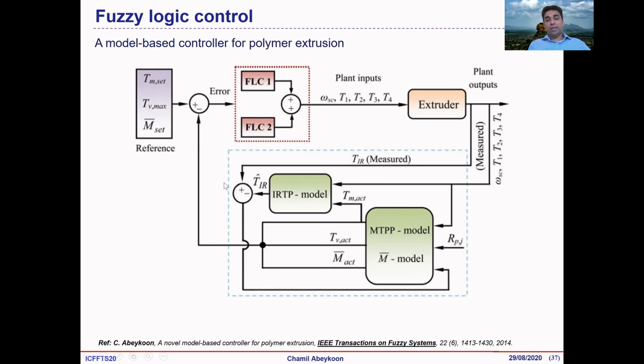Based on that, an error signal is generated if the process deviates outside of these values. Here we use these two fuzzy logic controllers, and at the same time we use the soft sensor proposed in the previous stage. This soft sensor can predict or estimate the melt temperature profile across the melt flow. So the control gets some idea about the actual melt. That is why we thought this is a bit more intelligent, since it looks at some of the quality, at least the melt temperature profile across the melt flow, to make the control decision. So we integrate this soft sensor with fuzzy logic controllers, and define a fuzzy logic based control system to manipulate screw speed and set temperatures to maintain the process within the reference range.